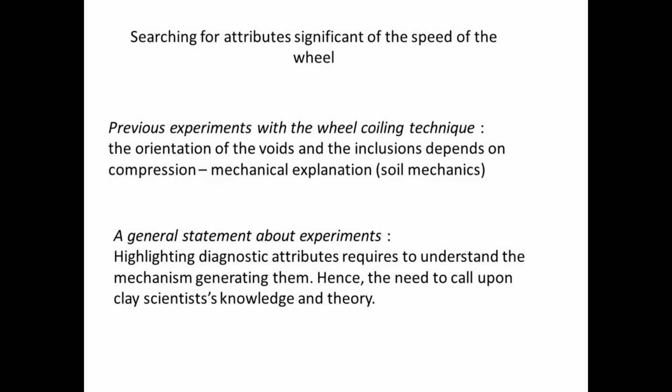Along the same lines, the highly interesting experiment designed to understand how local low-quality clay material in the medieval Bohemian-Moravian highlands needed to be matured for wheel-throwing vessels would deserve an explanation in terms of clay behavior. Clay scientists have indeed shown that long maturing periods result in the development of organic clay gels. They act as lubricating substances during wedging, favoring the cohesion and movement by shearing of the clay domains, thus optimizing the plasticity of the clay.